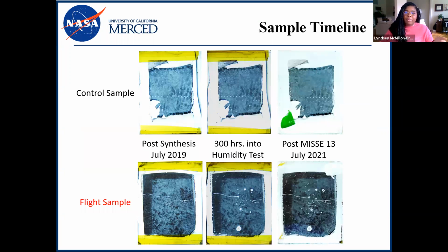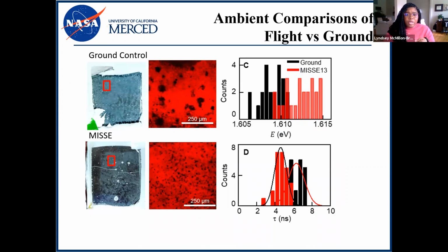So here I want to briefly compare the flight sample on the bottom and the control sample photos on the top, and each are really largely unchanged across the timeline of the experiment. So here we're looking at confocal fluorescence images of our samples being excited by 430 nanometer light. And you can see on the ground control there, or on each sample actually, there are dark regions that don't emit. But the density and the size of the non-emitter regions are different between the ground and the flight sample.